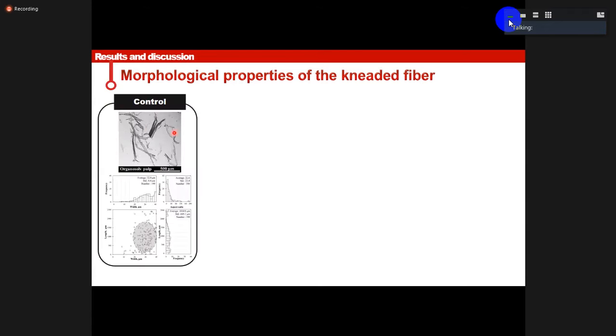This slide shows morphology of the organosolv pulp and kneaded pulp. This figure is an organosolv pulp used as control, and the distribution of fiber length and fiber width is shown in the graph. So you can see the particle size distribution on the graph at the bottom left. The x-axis is the fiber width and the y-axis is the fiber length. Control had no fibrillation on the surface of the fiber.